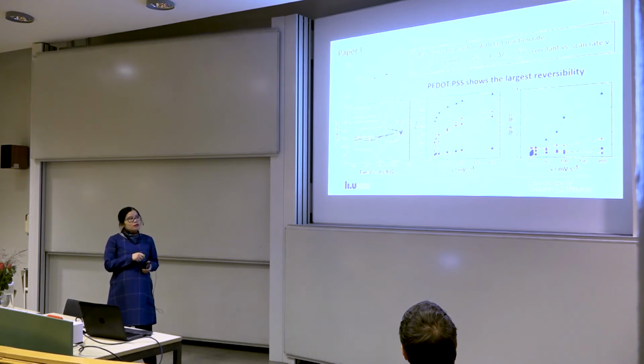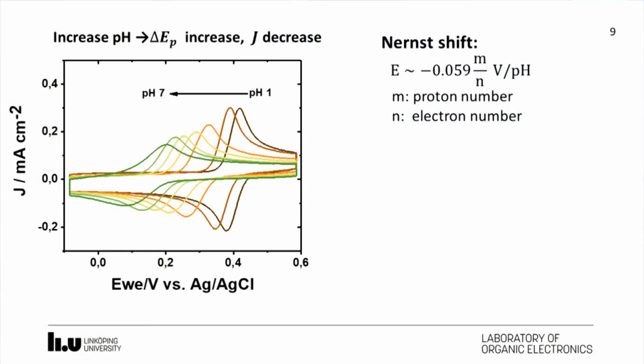words, the performance shows that efficient proton conduction is very important for these reactions, which makes PEDOT:PSS the best electrode. We further prove this by doing the experiment in electrolytes of different pH. With the increase of pH, the peak position shifts to negative values as predicted by the Nernst equation. That makes sense.